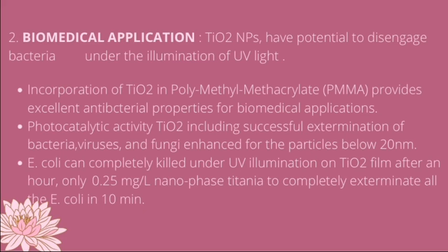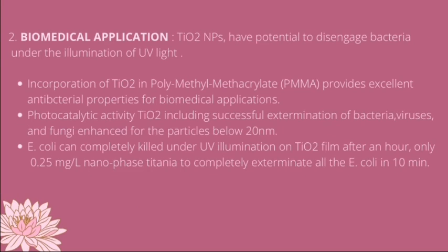The photocatalytic activity of titanium dioxide, including successful extermination of bacteria, virus and fungi, is enhanced for particles below 20 nanometer. E. coli can be completely killed under UV illumination on titanium dioxide film after an hour, but 0.25 milligram per liter nanophase titania completely exterminates all the E. coli in 10 minutes.